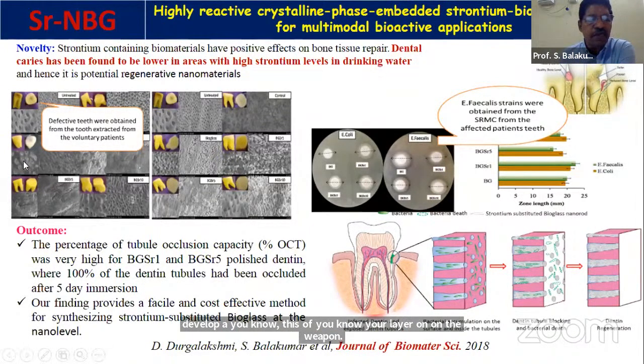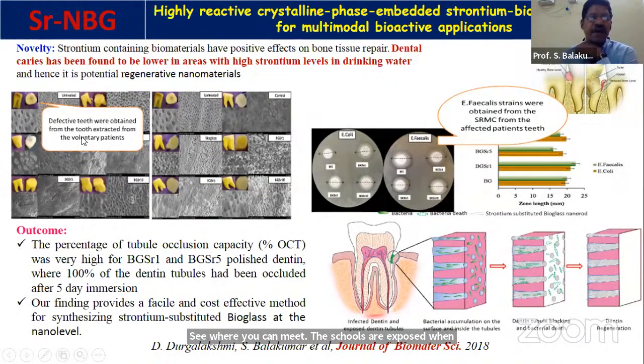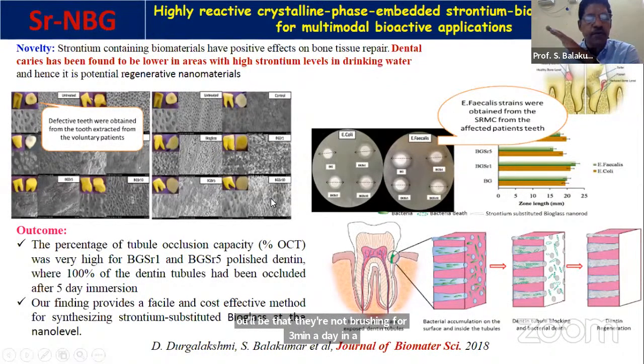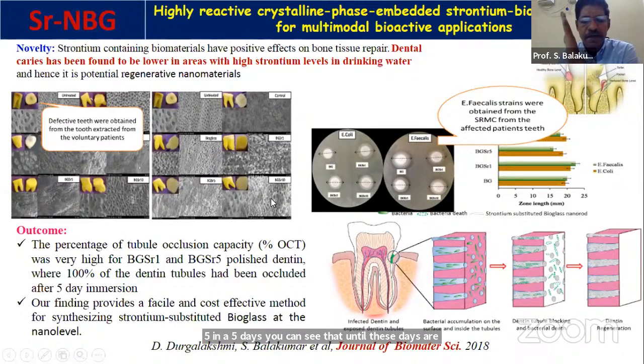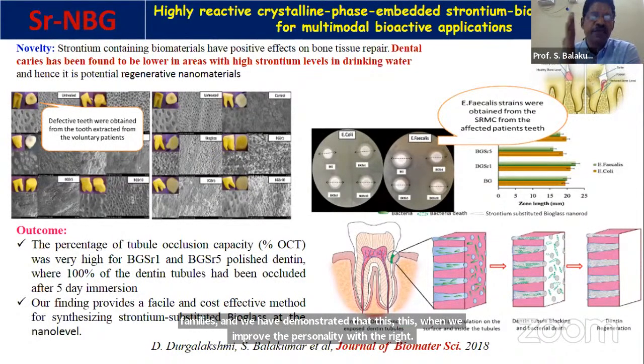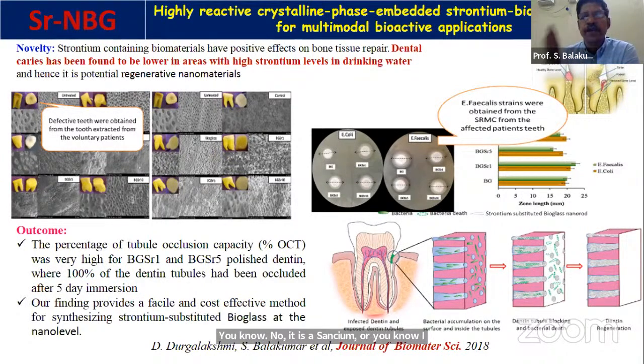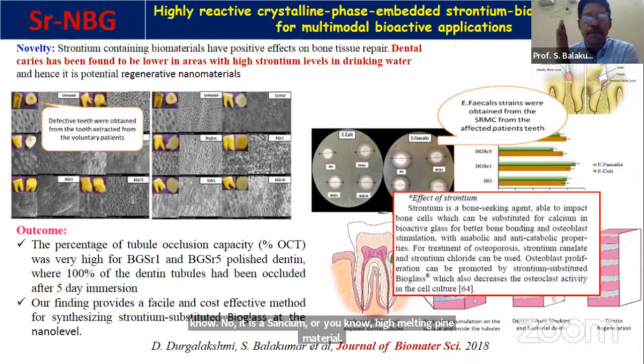With brushing for 3 minutes a day, in 5 days, you can see the dentin tubules are completely closed. This material is qualified, and we have also worked with one of the local colleges, Ramachandra Medical College, and we have demonstrated this. When you improve the crystallinity, with a high melting point material, it is possible to enhance the mechanical as well as antibacterial properties.